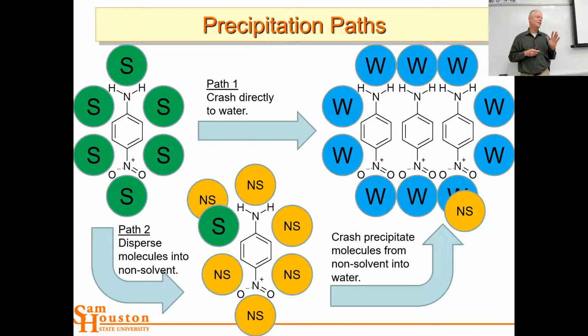So essentially, we've now replaced the cage, statistically replaced the cage around that solute with non-solvent molecules. And then we go from that into water, again at a 1:9 ratio. So we have a 1:10 dilution in each of these steps. So even though we're originally going straight into water, a huge dilution in water, now we're going through 2 steps, a 1:10 dilution each step.